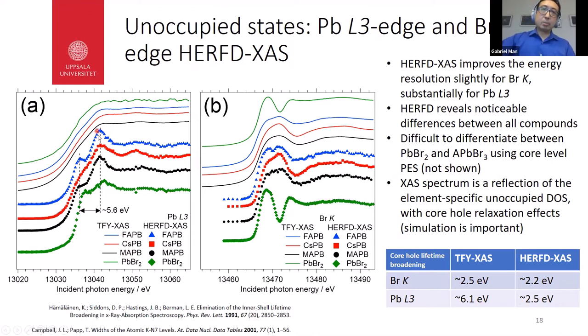When we compare blue, red, and black, the three perovskite compounds, we can see that they share similar features, but the sharpness of the features is quite different. We can already qualitatively see that for the case of blue, formamidinium lead bromide, the lead bromide octahedra seem to be less distorted internally compared to the red one, cesium lead bromide.